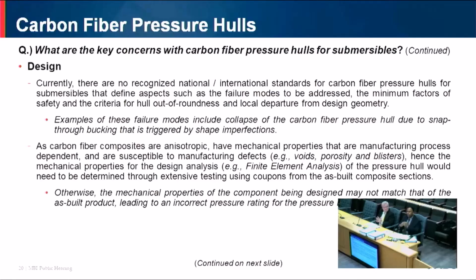After it's sent to the lab for testing, you will evaluate various mechanical properties. These include the tensile properties, what's the ultimate tensile strength, what's the tensile modulus, the compressive strength, the flexural strength, the shear strength. All of these properties are evaluated, and then you'll get the test results. And those test results are what is used for your design analysis. Okay. So if you don't use those test results, what you design may not match what you have produced. Okay. This is a little different from traditional pressure hull materials, because when we do the design review of traditional pressure hull materials, the material allowables and the mechanical properties come from the material specifications. Okay, you typically do not use the as-tested mechanical properties because they may exceed the material allowables. If they don't meet them, the material is rejected. Okay, but the as-tested properties are typically not used when you design pressure hulls made of steel or titanium, because the properties you use there come from the material specification. Those define the minimum acceptable properties.